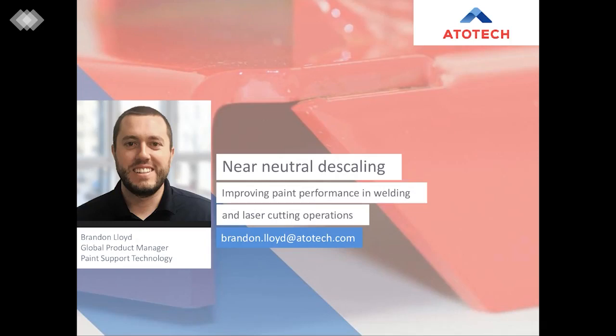Yeah. So again, I think that we've somewhat answered this in a few questions, and it's really dependent on a couple of things. It depends on the level of oxide scale on the welds or laser cuts. It's dependent on the application type, if it's immersion or if it's a spray application. But the UniPrep AC products would certainly be able to remove the scales as necessary, but it would come down to finding the appropriate operating parameters to remove those scales. With such a short application, again, depending on if it's immersion or spray application, it may require elevated temperatures or a higher concentration or something like this. But with the time being stagnant, those are really the two factors that can be adjusted to improve the rate of descaling.